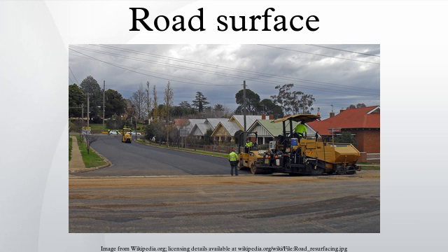Cold-in-place recycling. Bituminous pavement is ground or milled into small particles. The asphalt millings are blended with a small amount of asphalt emulsion or foamed bitumen, paved and compacted, allowed to cure for 7 to 10 days, then overlaid with asphalt. Hot-in-place recycling. Bituminous pavement is heated to 250 to 300 degrees Fahrenheit, milled, combined with a rejuvenating agent or virgin asphalt binder, and compacted. It may then be overlaid with a new asphalt overlay.